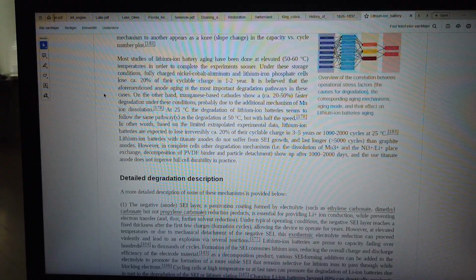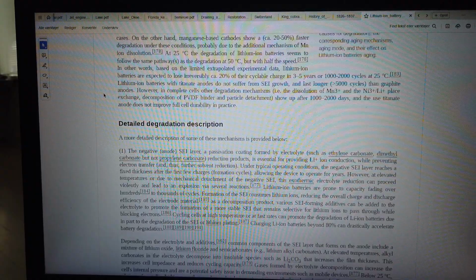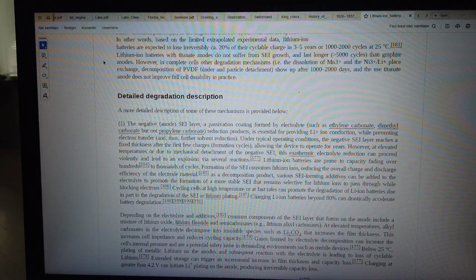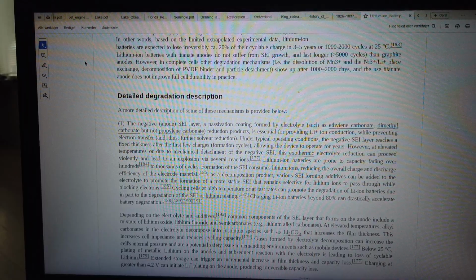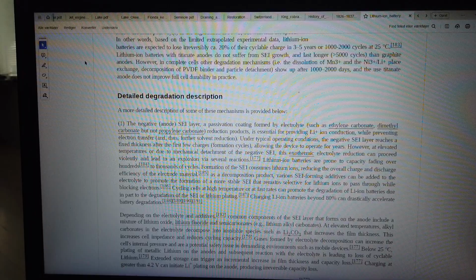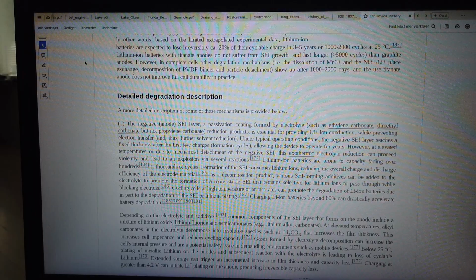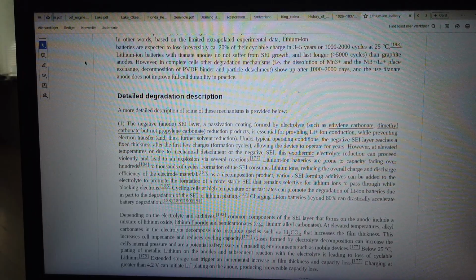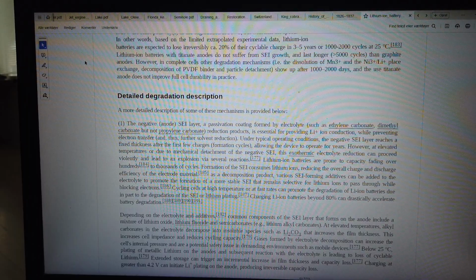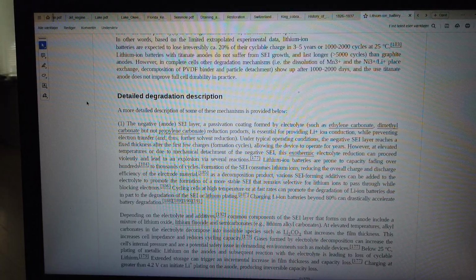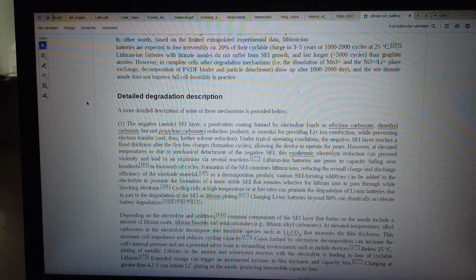Lithium-ion batteries with titanate anodes do not suffer from SEI growth, and last longer, over 5000 cycles, than graphite anodes. However, in complete cells other degradation mechanisms, i.e. the dissolution of Mn3+ and the Ni3+/Li+ cation exchange, decomposition of PVDF binder and particle detachment, show up after 1000-2000 days, and the used titanate anode does not improve full cell durability in practice.